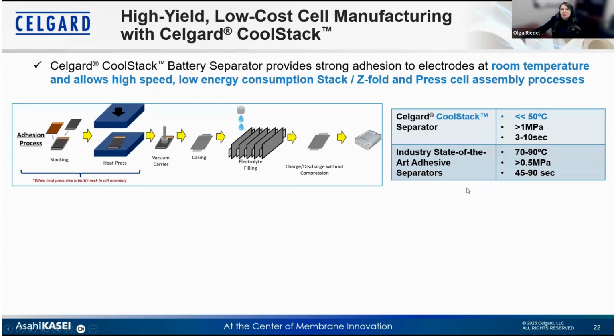Our CoolStack separator, as mentioned, can be pressed at room temperature for as little as 3 to 10 seconds. This is vastly different from state-of-the-art adhesive separators that usually need to be activated at 70 to 90 degrees C, and also require press times of about 90 seconds for really large and thick stacks.